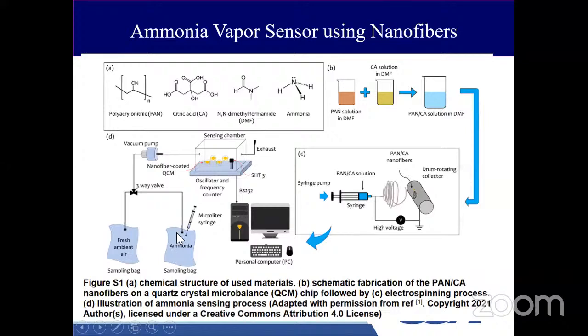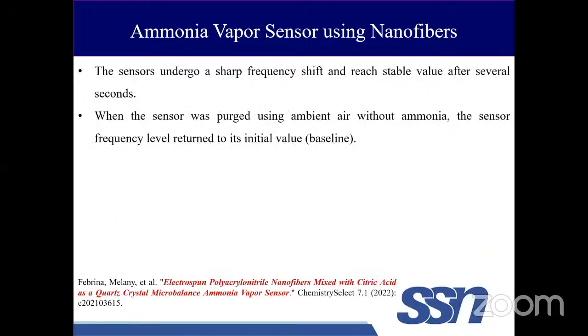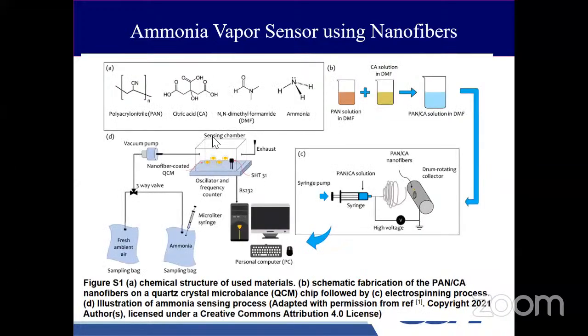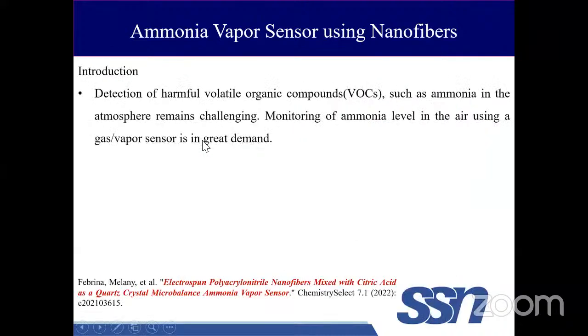As we all know, whenever we apply an electric field, the piezoelectric material is going to oscillate at a resonant frequency. Whenever ammonia is injected into the sensing chamber, as the citric acid and the ammonia have a tendency to interact, the resonant frequency changes. This is the principle behind it. The sensor undergoes a sharp frequency shift and reaches a stable value after several seconds. Whenever pure ambient air is purged into the sensing chamber, the resonance frequency comes back to normal. By this way, they can clearly detect the presence of volatile organic compounds.